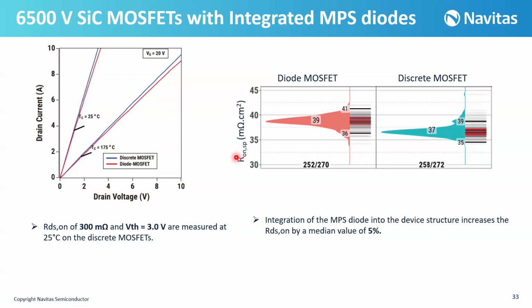And here is a comparison of RNSP for both diode MOSFETs and discrete MOSFETs. Obviously, you can see that the discrete MOSFETs have a lower RNSP compared to diode MOSFETs. As we mentioned, we are sacrificing one part of the active area, which means that we are increasing the RNSP. But the difference is only 5%, not more. So RNSP of the discrete MOSFET is 37, and the diode MOSFET is only 39 milliohm centimeter square, only 2 milliohm centimeter square difference. These diode MOSFETs show RDS(on) of 300 milliohm with a VTH of 3 volts.